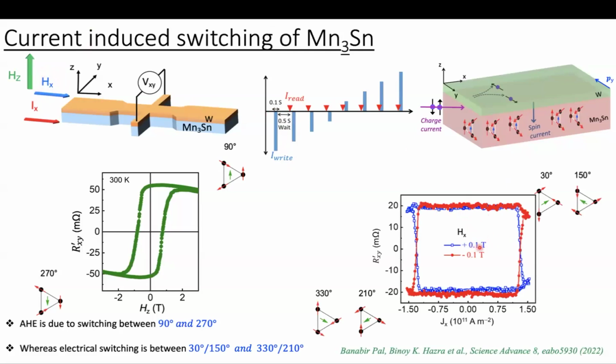When the bias field is positive, we see this blue curve. And when we reverse the bias field, the polarity also changes. This is typically observed in spin orbit torque induced magnetization switching. Here one can see the switching magnitude. The change in the Hall resistance is nearly 40 milliohm. If you calculate the switching percentage, that is only 40%. The reason is that here the 90 and 270-degree domains are not playing any role. The other four domains, 30-degree, 150-degree, 210, and 330, are playing a role. So the domain switches, let's say, from 30 to 210 or 150 to 330.